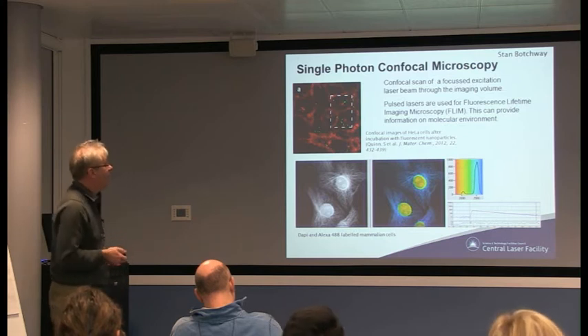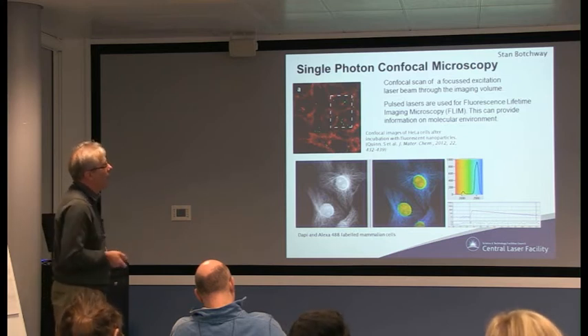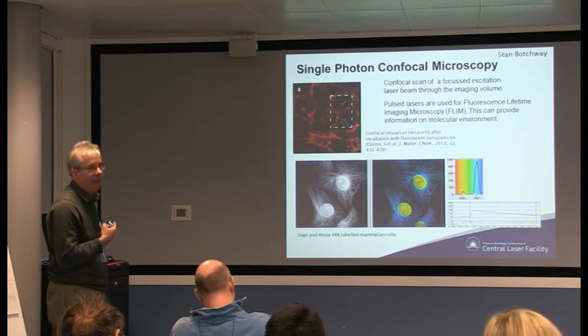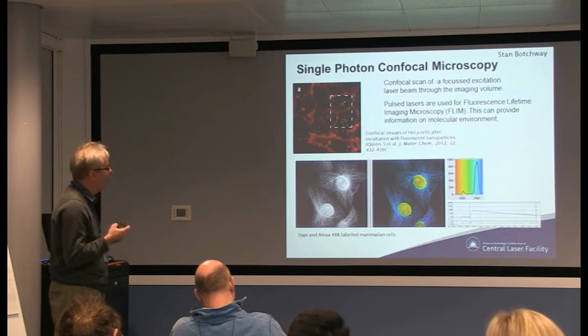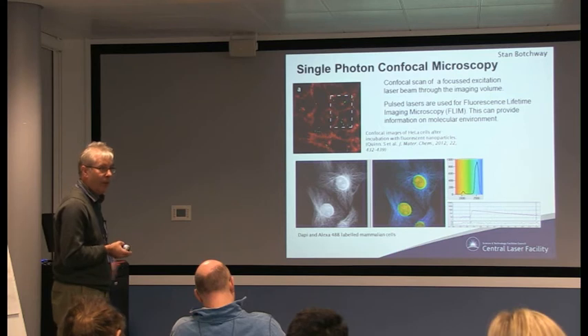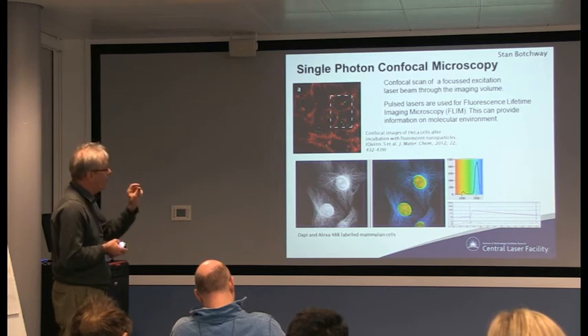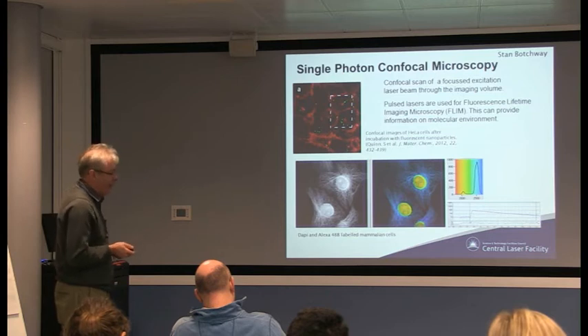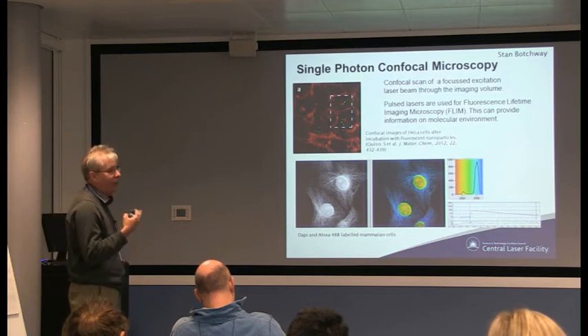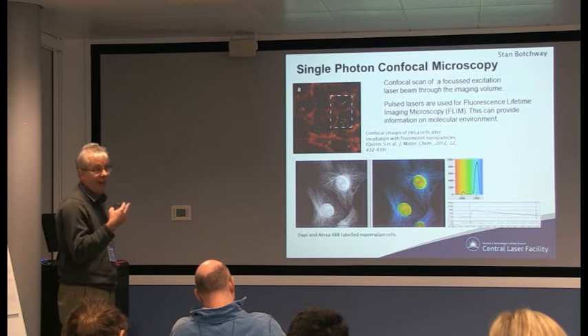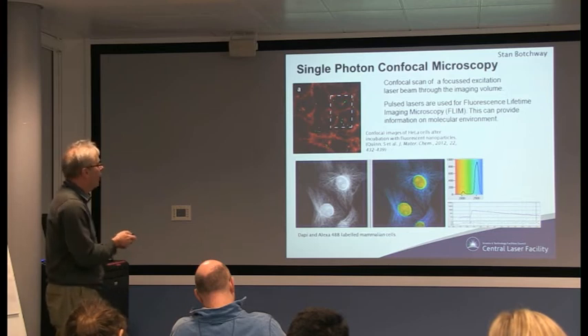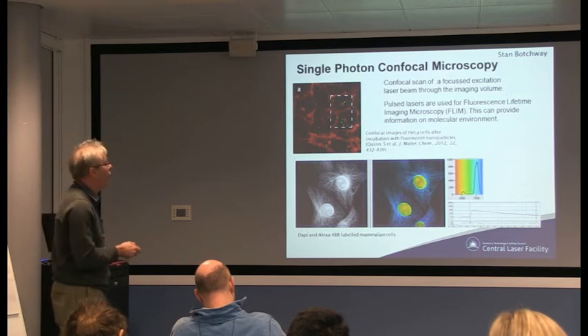The confocal bit comes into how you collect the light. We use a pinhole to collect the light coming back from the sample, so we can really refine or well-define the collection volume. Typically when you use the pinhole, you'll be collecting from a focal depth of only a micron, or even less than a micron. That's actually quite good - it reduces a lot of the scattering, background noise, stray laser light, etc. that's in the sample, so you can get a very well-defined image.